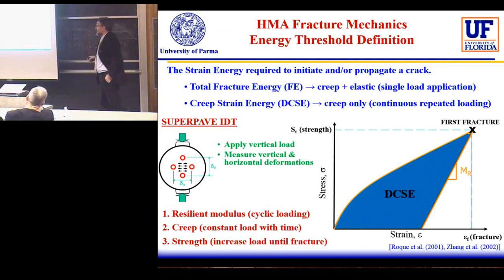As was designed, everything was calculated following the Superpave IDT procedure, that is based on the IDT test and a series of 3 different tests carried out on the same specimen, applying load and measuring vertical and horizontal deformation. We have the resilient modulus with cyclic load application, the creep with static constant load over time, and after that the strength, increasing the load until failure in a strain control test.